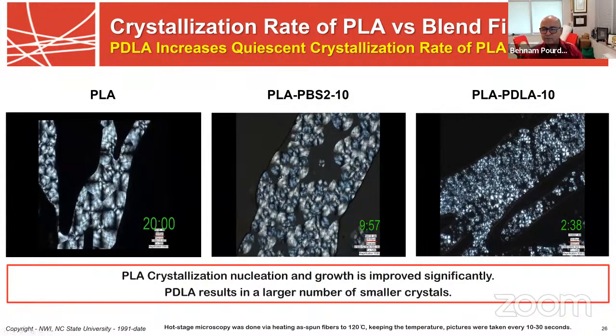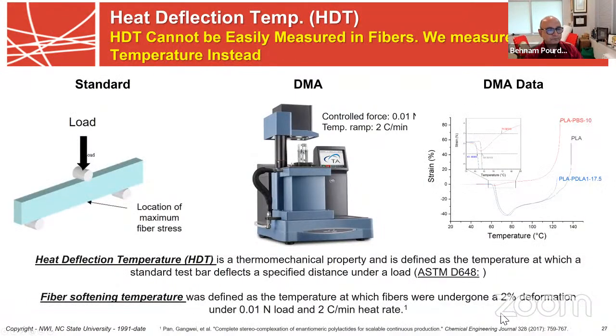And that's really good for many reasons, because especially in thermal bonding of nonwovens, we really like small imperfect crystals because that facilitates your bonding at a lower temperature, and of course a higher crystallization rate means that you have a higher reptation, and that means better chain entanglement at the bond spot, and you get a better performance in the material.